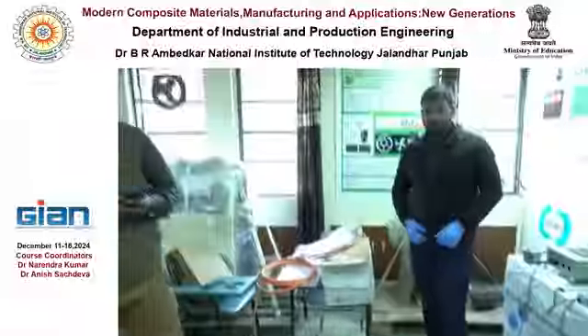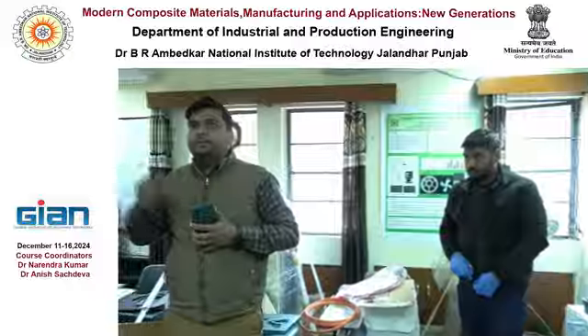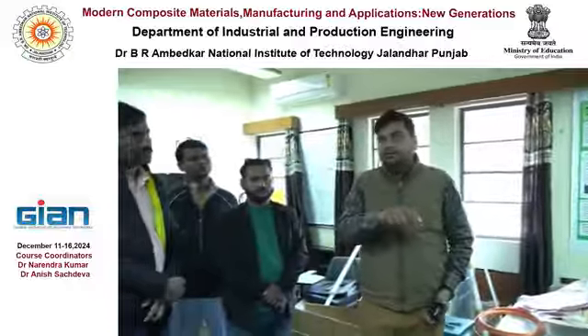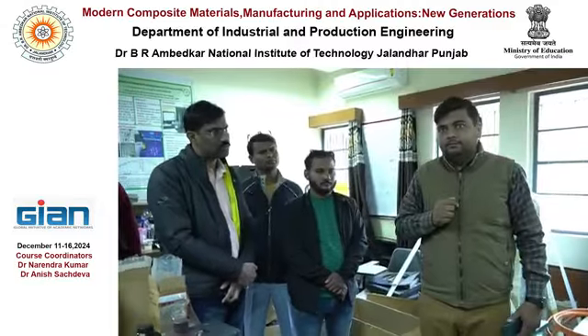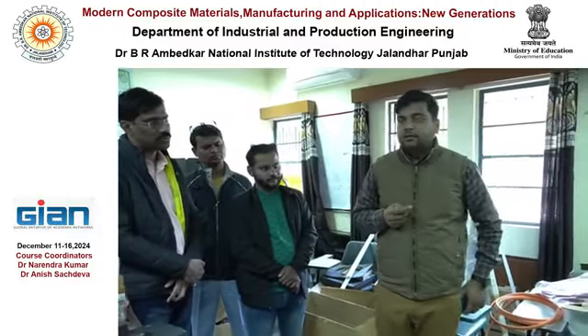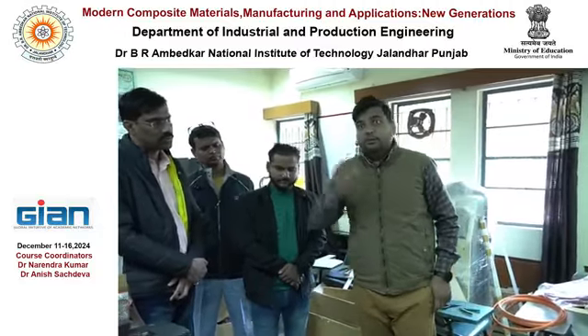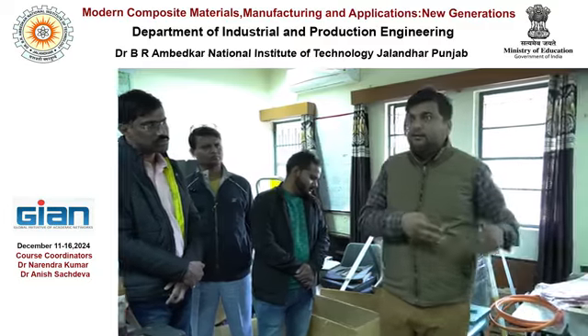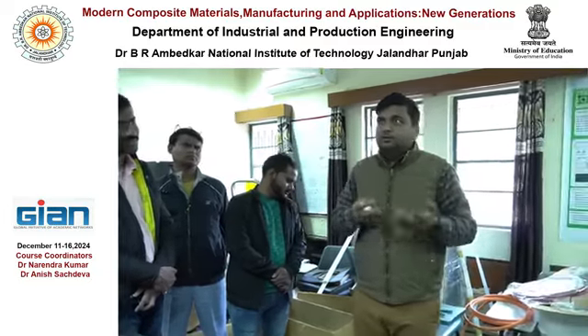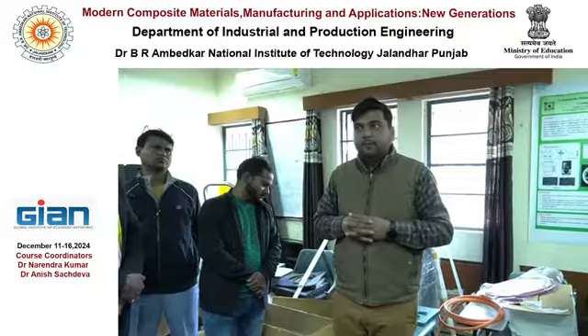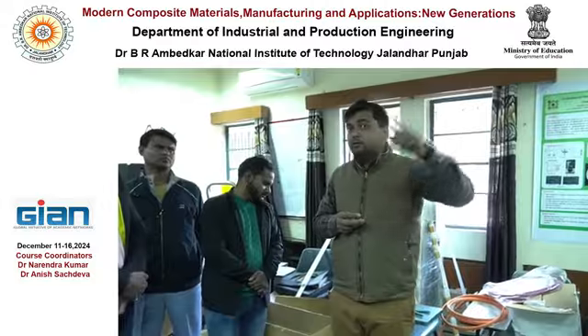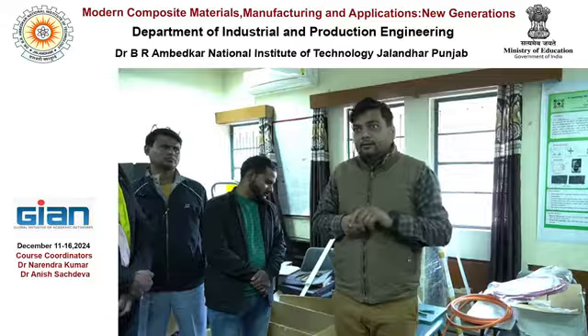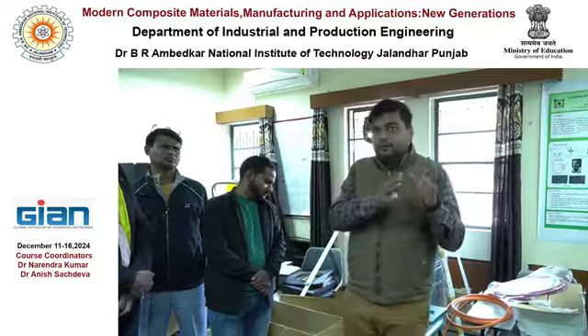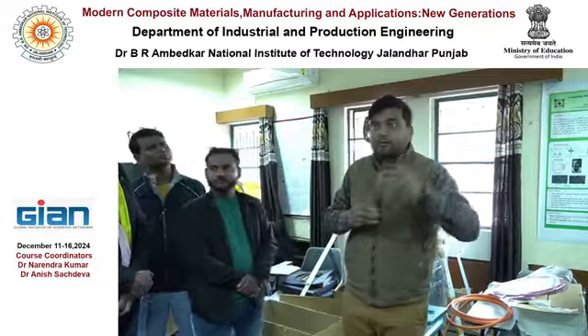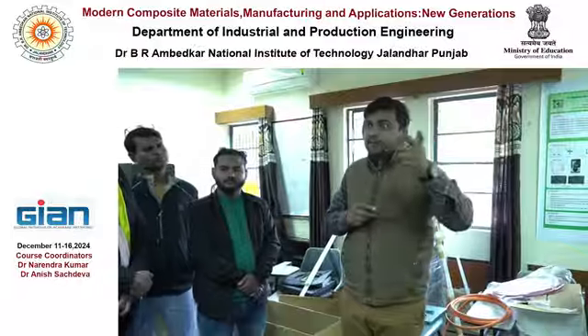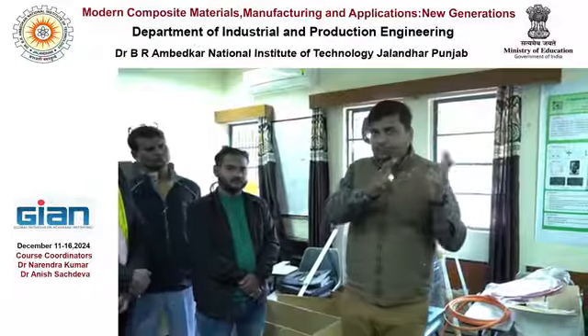Because I want to discuss one of my cases, because during my PhD I was mixing EVA and graphite, right, with the help of this magnetic stirrer. What happened, after one day, 24 hours actually, I checked whether they had mixed or not. I found they were not mixed together. Why? Because I didn't go through the literature properly. So I found that I should raise the temperature also. Then only it will mix, right? So then I found that temperature value.